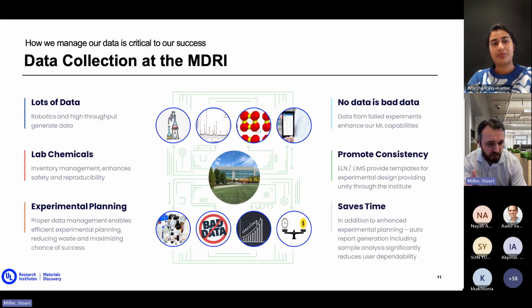And MDRI, the largest focus that we've had, and I mentioned earlier in the presentation, we spent over 18 months, about 20 months now, cultivating how we collect data. It's because we generate so much of it and we're in complete control of that data. We know, as I said, the lab chemicals, the inventory, we do the experimental planning, and one of the things that's typically traditionally done is we don't report bad data.